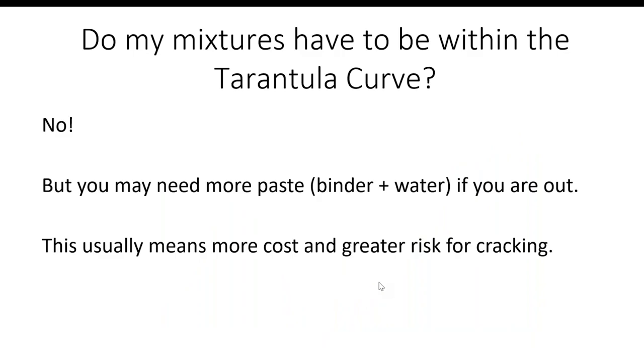So do my mixtures have to be in the curve? No, they don't have to be. But if they're not, you're going to need more paste or you're going to need more admixture to make it a workable concrete if you're out. This usually means more cost. This usually means a greater risk for cracking. And so a lot of people want to avoid this if they can.